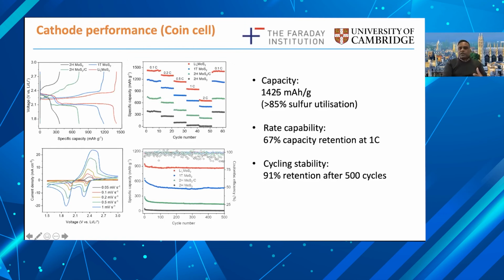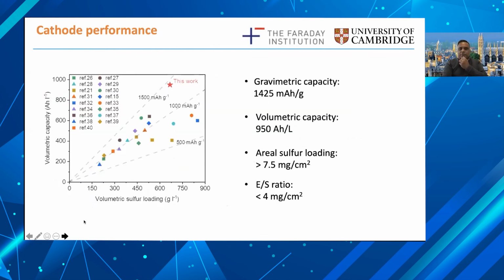But when one looks at the overall capacity of these coin cells, it's extraordinary. It's on the order of 1400 milliamp hour per gram, suggesting that we have over 85% sulfur utilization. There's very good rate capability, and there's 91% retention over 500 cycles. But it's all very good, but the problem is that coin cells are not really practical. So if we compare our data with